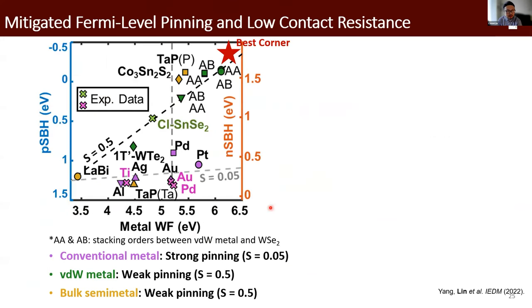Based on this, we computed the different materials, and when we plot the Schottky barrier height versus the work function, similar to the curve I just showed you at the very beginning, ideally we want the slope to be close to one. For a conventional metal, the slope is very low, 0.05, and for the two strategies we proposed, the high work function semi-metal or the van der Waals metal contacts, the slope is around 0.5. That means the Fermi level pinning effect is indeed mitigated, and we have identified a couple of good materials for the P-type contact.